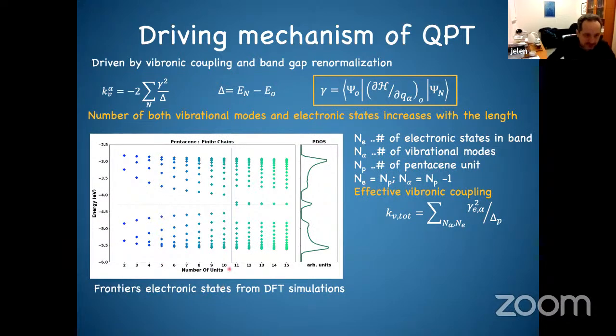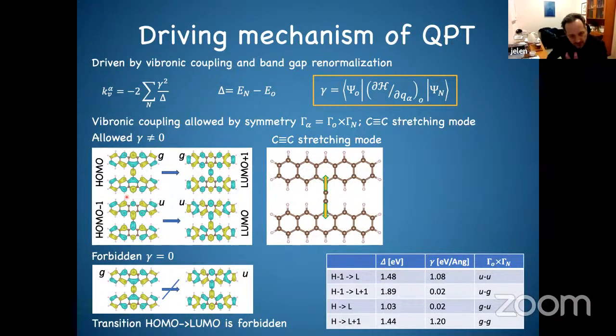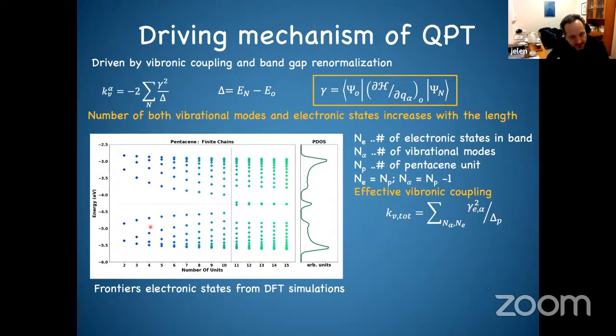So now I can do the calculation in DFT, and here what I see is the transition happens at a different stage. It happens between 10 and 11, which is in disagreement with experiment. But of course, we know that DFT is not doing a very good job for this kind of excited state. But still, we can capture this transition in DFT, but it occurs for shorter chains. But now, let's have a look at this effective vibronic coupling, because what you see here is when I make the system larger and larger, I'm developing some kind of bands. So for the dimer, this is what you've seen here. This is my HOMO-LUMO. I have only 2 species, but if I go to the trimer, I already start to have 3 in valence and 3 in conduction band, 4, etc.